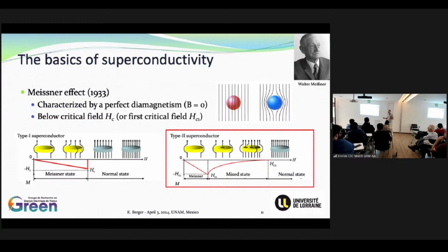And in fact, there are two categories of superconductor. What we call type 1 has a very low critical field. So usually this type of superconductor is not used in electrical engineering applications, since we are reaching hundreds of millitesla or several Tesla. So this type is not useful. So we are using what we call type 2 superconductors. And for these superconductors, there are two critical fields. The first one, where there is a complete expulsion of the magnetic field. And the second critical field, where the superconductor is not superconducting anymore. It's called the normal state. And in between, we call it the mixed state.